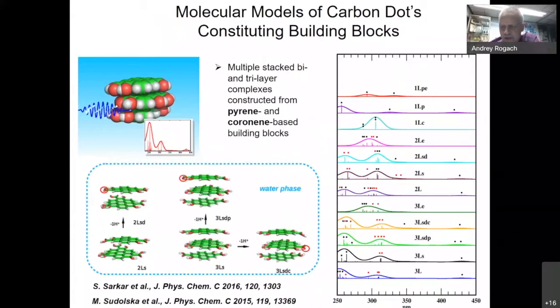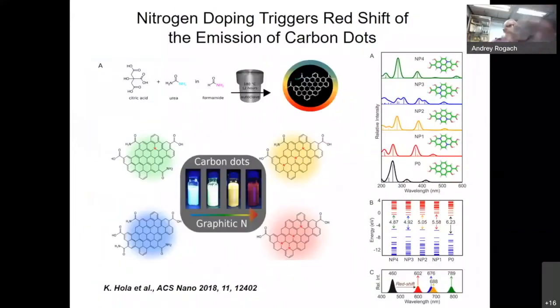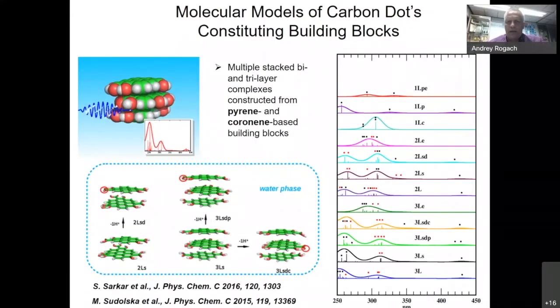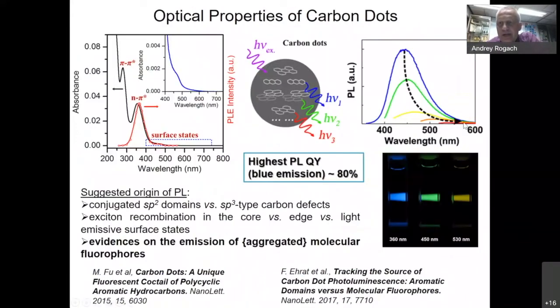Okay, so this picture I already showed you. And my next point is that nitrogen doping is very important here, because nitrogen doping will trigger a red shift of the emission of carbon dots. So most of the time, when people make carbon dots, they will make materials which emit blue light. And the photoluminescence quantum yield for this blue emission can be very high.